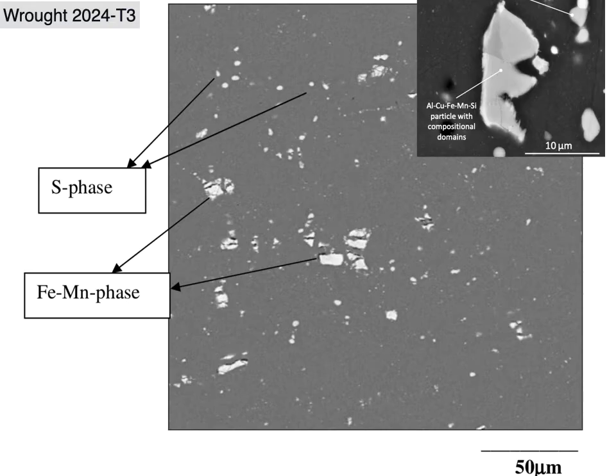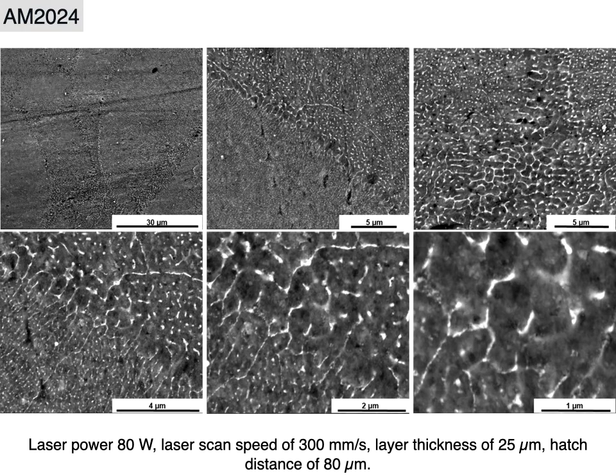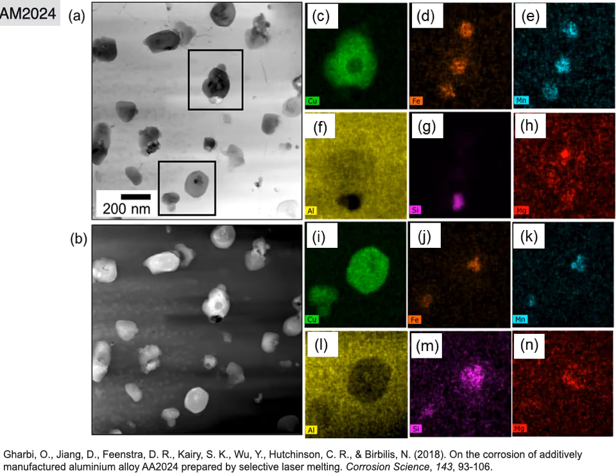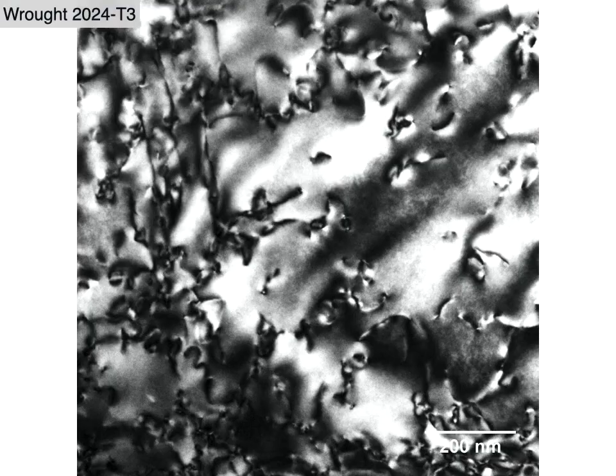Compared to the wrought microstructure, that's well known and includes many constituent particles of appreciable size, in the micron and tens of microns of length scale, and then forming clusters that could often be even 100 microns in size. We have a very different microstructure in the additively manufactured 2024, as you can see here. So the microstructure is very refined. On the nanoscale, we see the hardening phases, and here what we see is the hardening phase is actually a doped aluminium copper phase, not the S phase that's normally seen in wrought 2024 that is associated with dislocations,